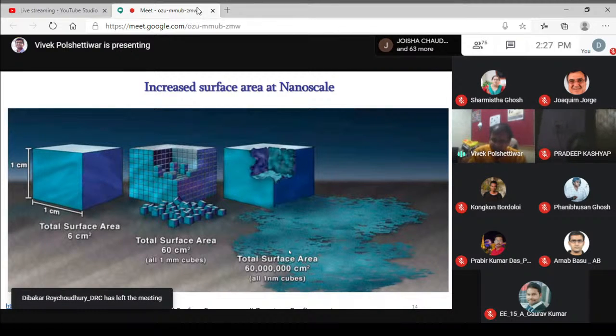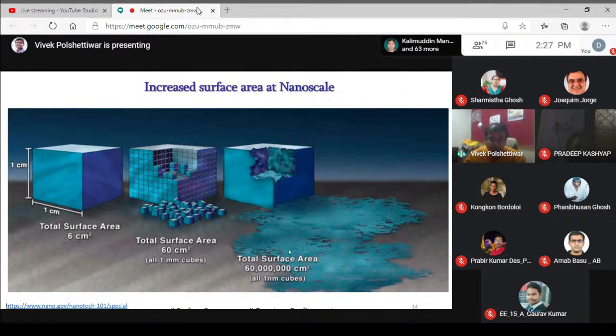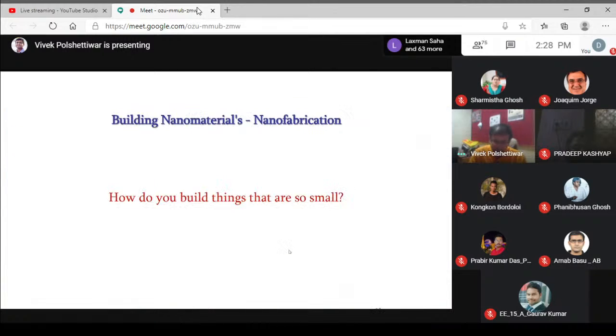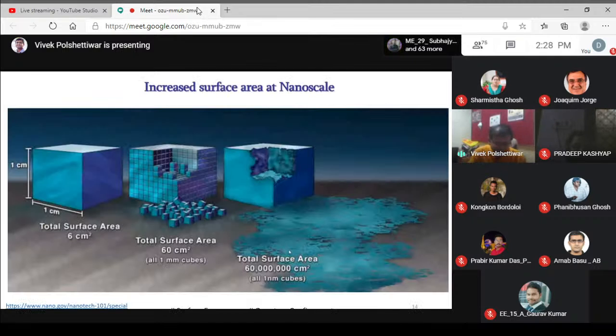And when I say an increase in the surface area, what happens? You have most of the atoms on the surface, right? So they will have a low coordination number, so the atoms will have a higher number of uncoordinated bonds. We call them dangling bonds, which give them high surface energy and make that surface really reactive. That's why it reacts and shows unusual properties. In addition, several other things happen, like quantum confinement and energy level splitting, that allow you to tune the optical properties of the material in addition to the physical properties.